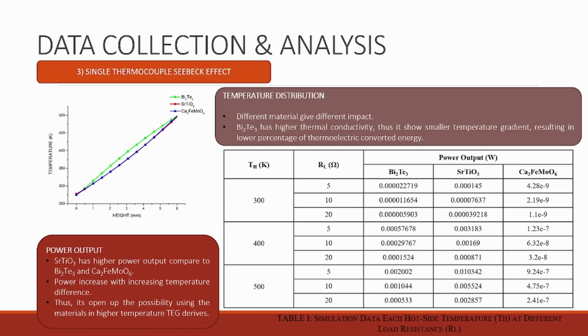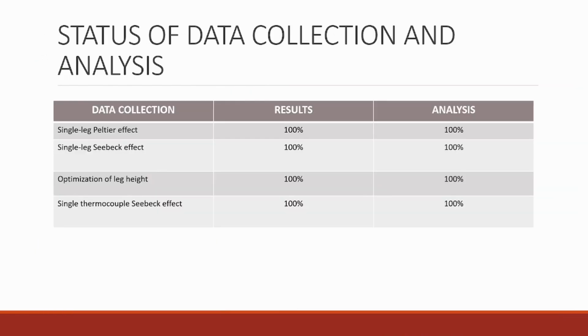For the single thermocouple Seebeck effect, the temperature distribution is different for each material. Bismuth telluride shows a higher thermal conductivity. It shows a smaller temperature gradient, resulting in a low percentage of thermoelectric converted energy. And for the power output, strontium titanate has a higher power output compared to bismuth telluride and calcium manganate. Power increases with increase in temperature difference, thus opening up the possibility of using this material in higher temperature TEG.